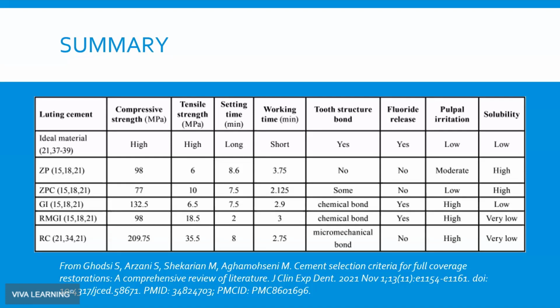The tensile strength's a little bit different. Now, obviously, if you meet or exceed, and keep in mind, these numbers are fairly arbitrary. My eyes were opened as I started spending more time and doing more work for BISCO, exactly what these numbers are. So it's hard to really put a real value to them other than to say, view them relative to other numbers in the same category. The tests themselves are, I would argue, hardly meaningful in regards to a clinical situation. But certainly going from, let's say, a tensile strength of 6 from zinc phosphate to 10 in zinc polycarboxylate is meaningful and significant.